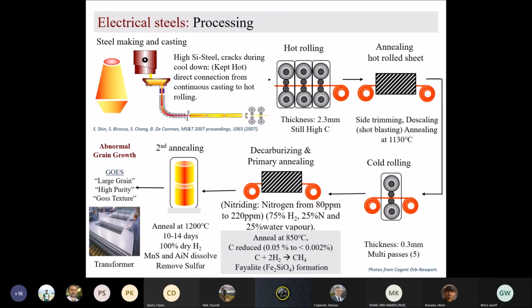Through that, we are reducing the energy, because when you cool it down, you need energy to heat it up again for hot rolling. By the direct connection between continuous casting and hot rolling, you save energy. Also, if you leave high silicon steel, anything above 3, to cool down freely after continuous casting, it will crack. To avoid that, most companies nowadays, including Cogent Orb and Tata Steel in Holland, directly connect the continuous casting to hot rolling.